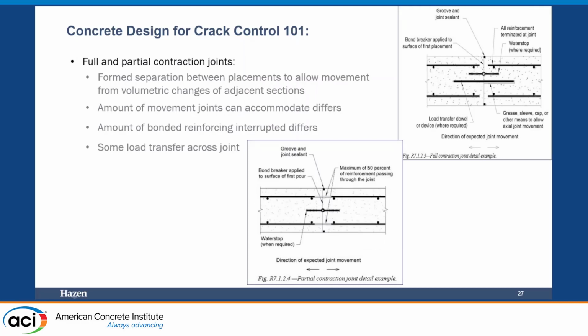Contraction joints subdivide into full contraction joints and partial contraction joints. Full contraction joints are in the upper right. Partial contraction joints are in the lower left. With full contraction joints, all your bonded reinforcing is discontinuous. Slip dowels will allow linear movement along the plane of the wall to occur. But this joint cannot transfer any bending, so it needs to be coordinated with the design engineer if used. In the event that they designed that wall to be continuous across that point, this joint would not allow that